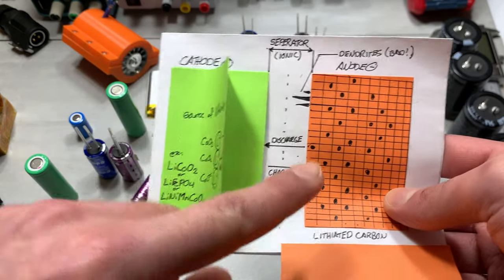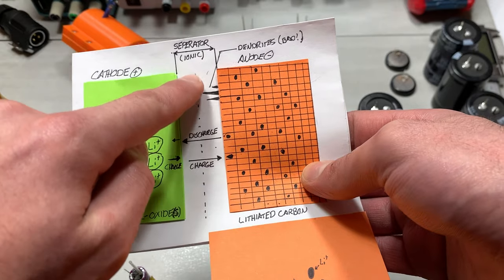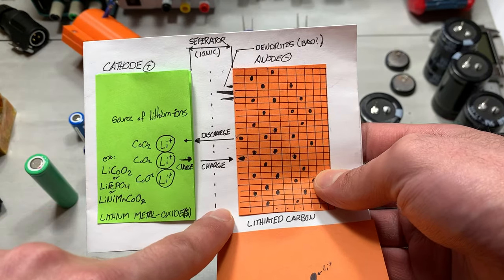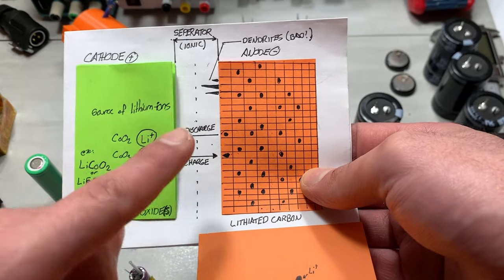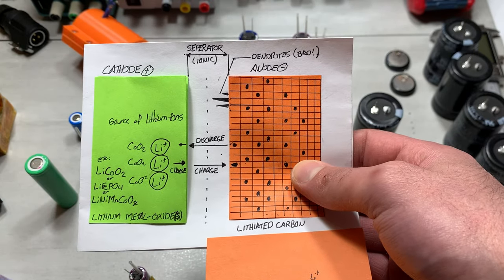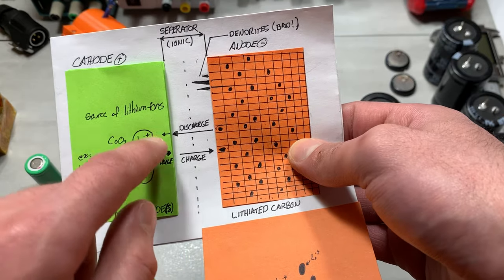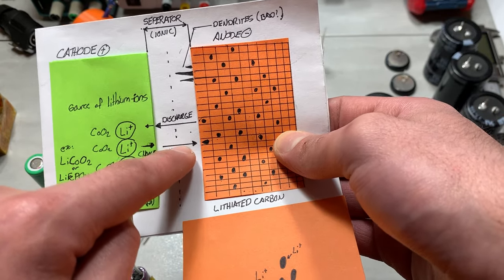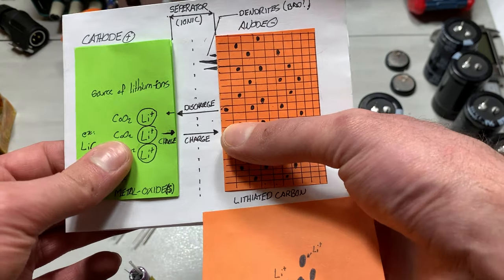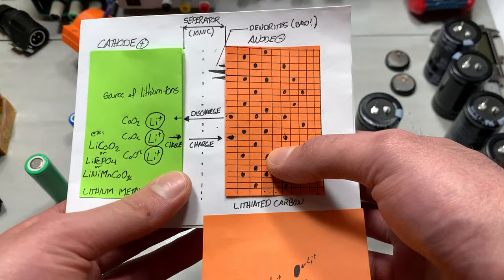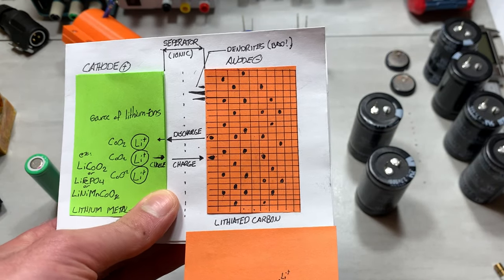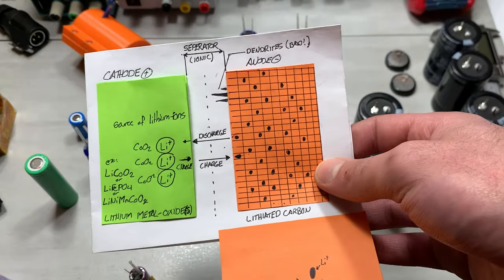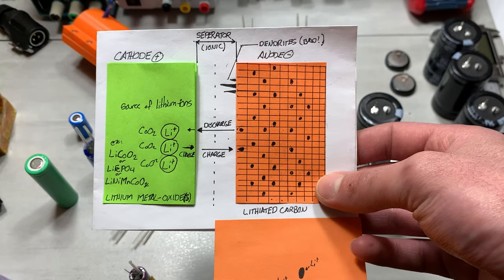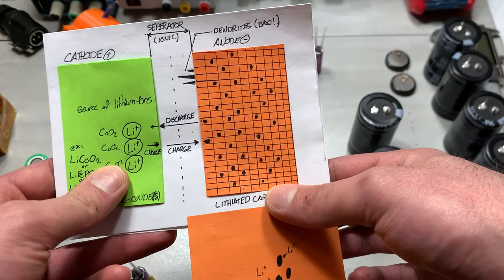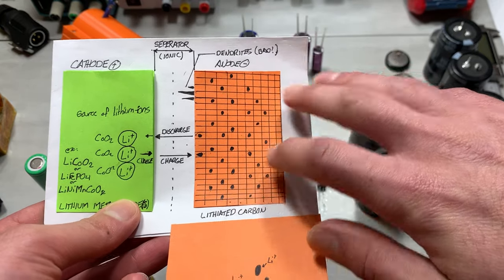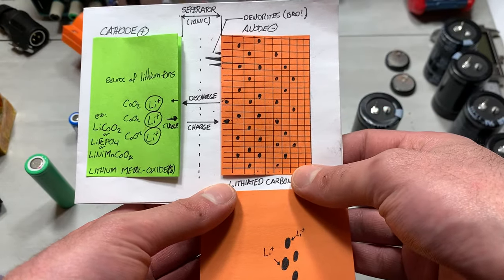And then, very similar to in the lithium ion supercapacitors, you have an ionic electrolyte solution, which is not water-based, which also contains a significant concentration of lithium ions. When charging the battery, the lithium ions from the cathode are carried by the electrolyte into the anode and are intercalated into the anode. Now, of course, there are several other chemical processes which take place in this. This is the overall reaction or chemical process behind the charge and discharge of a lithium ion battery, where during the charging process, your carbon anode is intercalated and essentially packed full of your lithium ions,